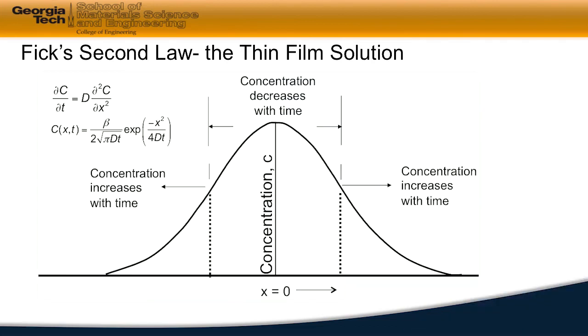Now, the actual solution to this, including all of the boundary conditions of this particular function, is given in this slide. And what we see is we can describe the change in composition, not only with position, but with respect to time. So we have two variables here, and this is then a partial differential equation. The term in the pre-exponential tells us about the geometry of the process. What's the cross-sectional area? It also describes for us how much mass we have in the material. And then in the exponential portion, x represents the location where we are examining the composition. And D and t have their normal meanings, D being the diffusivity, and t representing time. So what we're going to do then is to look at this equation and see how we might be able to modify this equation to describe another type of diffusion that involves slightly different boundary conditions than the thin film.